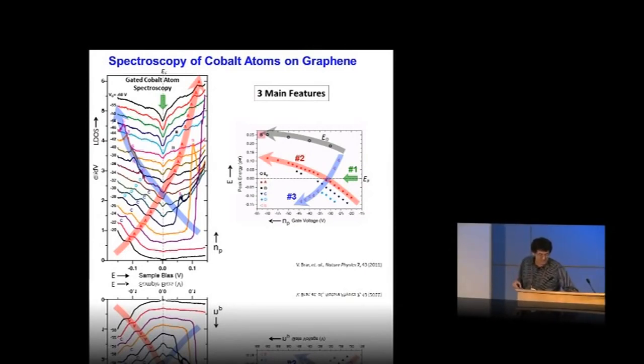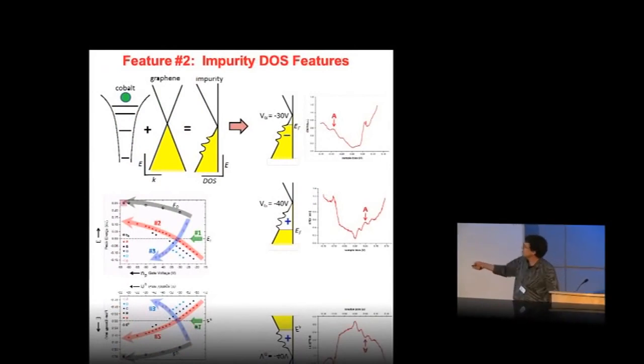The idea, which you can see in this little cartoon, is that the cobalt atom, an isolated atom, has atomic energy levels. If you drop it onto a piece of graphene, those atomic energy levels are going to hybridize in some way with the graphene, and that leads to defect states, which I have drawn schematically here. This is not the result of a calculation, just a cartoon. So here are our defect states in the density of states of graphene. We can see those defect states with the STM in our spectroscopy.